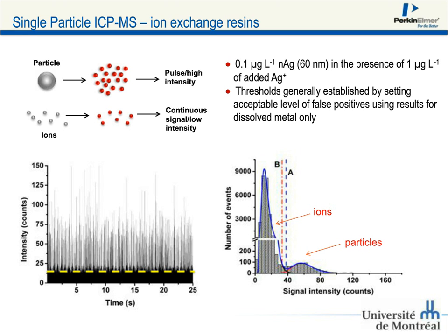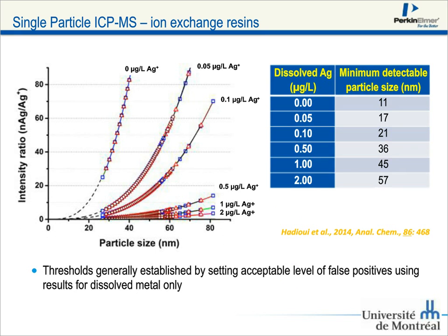In this case, on the left-hand side, we've set the dashed yellow line to distinguish between the ions and the particles, and that dashed line is seen by the dashed vertical lines in the right-hand side. Now, based on where you put that line, you're going to get more or fewer particles in your quantification. So what we've looked at is varying the dissolved concentration, which is essentially giving us a difference in the signal to noise, or the particles over the dissolved. And you see that here for a given intensity ratio, given signal to noise ratio. The more dissolved metal there is in the solution, the worse off you are. The harder it's going to be to detect those really low concentrations or really small sizes of particles.